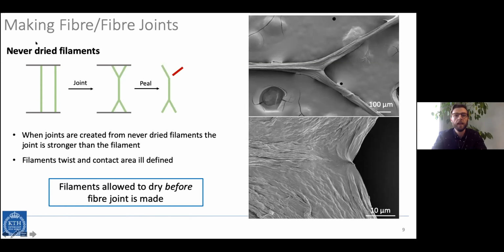So if we're thinking about making them from never-dried filaments, what we can do is take our filaments and suspend them between two supports and then touch them together and use capillary forces to link these materials together. You can see on the right here, this is what the result is. We can see we have this Y-shaped joint where we have individual filaments that have been joined. But if we look a little bit closer in the SEM, we can see that these filaments actually fuse together and become one uniform filament.